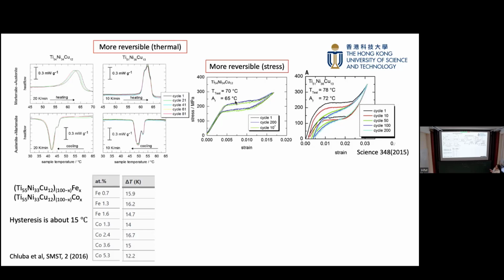So people are still making this material by very fine doping of the copper atomic ratio. So here, this one and this one only differ by 1 atomic ratio of the copper. And this is differential scanning calorimetry, which measures the transition temperature as we heat it up and the transition temperature as we cool it down. The difference is the hysteresis, and we can see that the hysteresis is different. And if we do thermal cycling, we find this one, the transition temperature migrates and the functionality changes. And this one is exactly on top of the cycle.